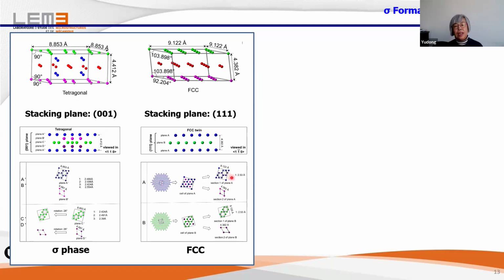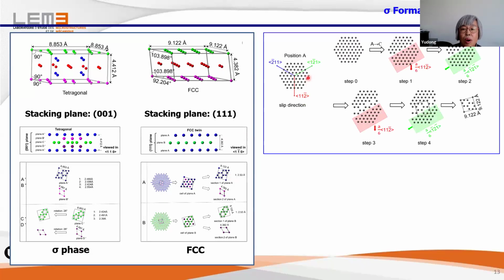Then we have to consider that this transformation is helped by stacking faults. If we put the 111 plane of the FCC phase here, we see we can make this part of the 111 plane move from position A to position C under the Burgers vector of this partial dislocation. We see here we have a distorted area. If we continue to move this part to the next C position with this Burgers vector, partial dislocation, then we further enlarge this distorted area.